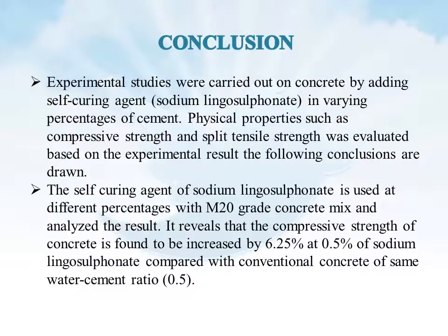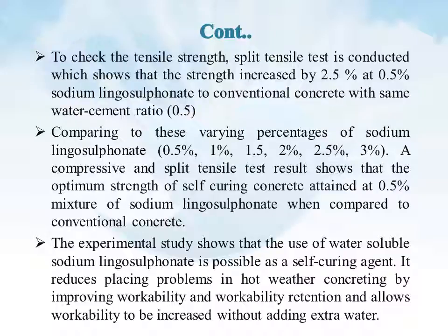Conclusion. Experimental studies were carried out on concrete by adding self-curing agent in varying percentages of cement. Physical properties such as compressive strength and split tensile strength were evaluated based on the experimental results. The following conclusions are drawn. The self-curing agent sodium lignosulphonate is used at different percentages with M20 grade concrete mix. The result reveals that the compressive strength of concrete is increased by 6.25% at 0.5% of sodium lignosulphonate compared with conventional concrete of the same water cement ratio. The split tensile test shows that the strength increased by 2.5% at 0.5% sodium lignosulphonate compared to conventional concrete with the same water cement ratio.